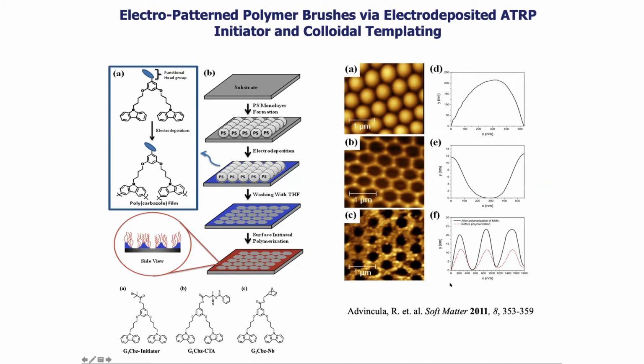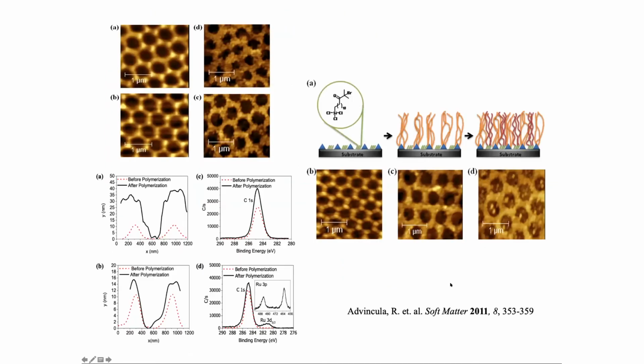And again, of course, since we still have a hole in the middle, we can backfill that. And then we can create a pattern within a pattern, or a polymer brush within a polymer brush, as shown here. The grafting of the ATRP initiator was done by silane assembly on the ITO substrate.